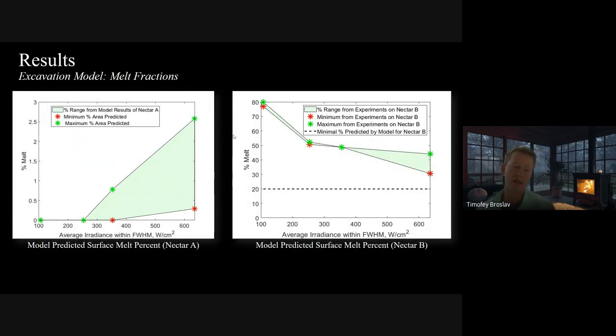Now, regarding the actual surface area of the melt, the model predicted somewhere in the range of up to 2.5% of the entire beam surface would cause melting, all the way up to at focus for Nectar A, meaning it's a very, very small melt percentage, which aligns very well with what was observed.